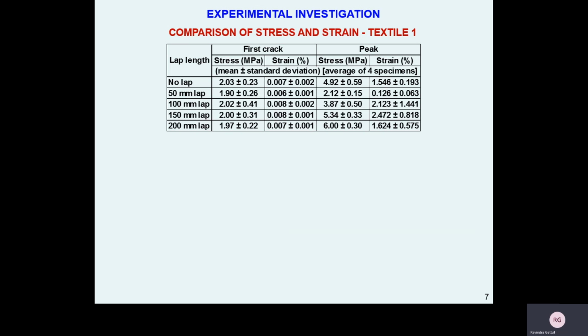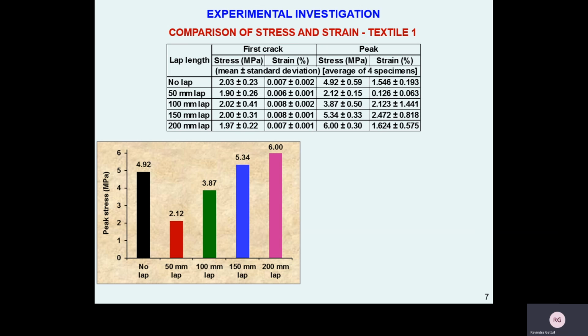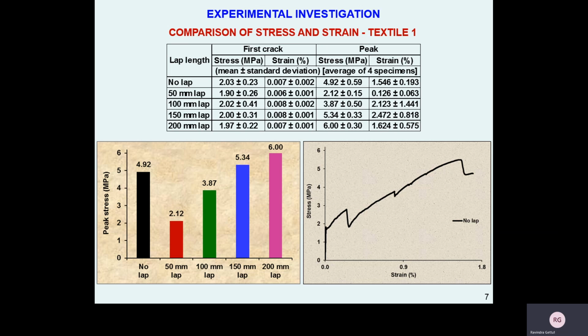Now coming to the test results. The table shows the average values of stresses and strains considered for 4 specimens in each case at the salient points of first crack and peak for the considered range of laps for the first option of E-glass textile with a smaller mesh opening. The data corresponding to peak stress depicted in the bar chart shows that for 50 and 100 millimeters of lap lengths, the stresses were much lesser compared to the no lap condition, and it necessitates the provision of at least 150 millimeters of lap for this particular textile to depict a behavior similar to the no lap condition. This is portrayed in the stress strain plot also, which shows the behavior of the composite without lap.